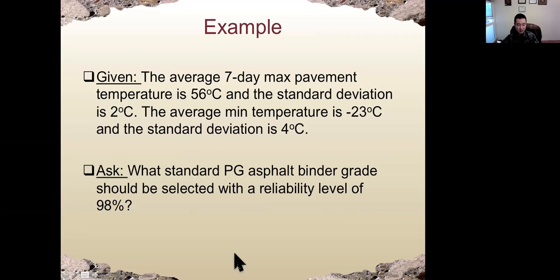So the question tells us the average 7-day max pavement temperature is 56 degrees Celsius, and the standard deviation is 2 degrees Celsius. We're going to use the standard deviation and the 56 degrees Celsius to calculate our design temperature. The average minimum temperature is -23 degrees Celsius, with a standard deviation of 4 degrees Celsius. Okay. So the question is asking what standard PG grade the binder should be selected with a reliability level of 98%.